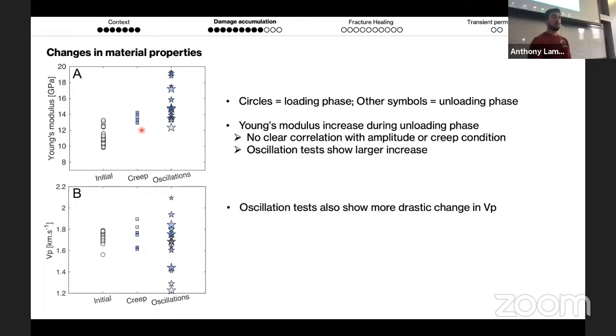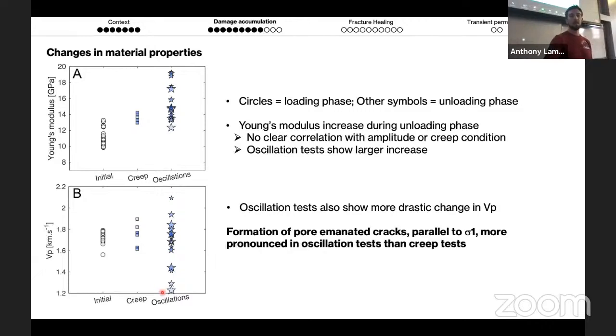In terms of VP, we have a similar thing that happens. Basically, that's before the experiments and again after the experiments. There's no clear correlation with creep oscillation, only that oscillation tests will result in a bigger change in VP after the experiment. So I've interpreted this as basically forming pore-emanated cracks during these oscillation tests. Well, in all the creep tests, but I form more pore-emanated cracks during the oscillation test.